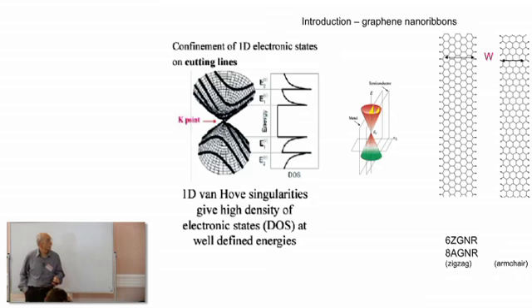It can give different kinds of electronic properties. For these ribbons, for example, with zigzag edges, we obtained semi-metal behavior, and when we have armchair edges, the electron spectra depend on width, when we change the width and change the electron wave vector in this direction, and these electrons move through this ribbon like electrons in waveguides.